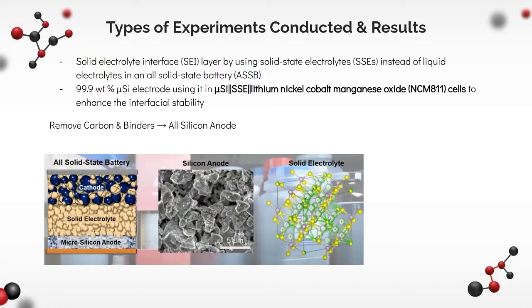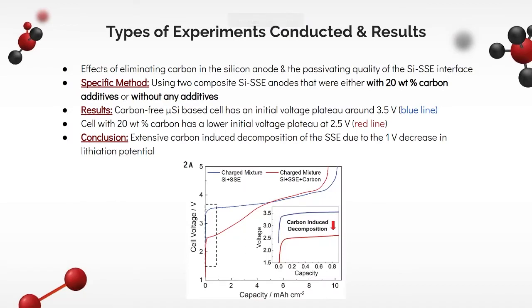Researchers removed all carbon binders from the silicon anode, since carbon is known to reduce the stability of sulfide solid-state electrolytes, promoting its decomposition. Researchers analyzed the effects of eliminating carbon in the silicon anode and the passivating quality of the Si-SSE interface. They prepared the samples using two composite Si-SSE anodes that were either with 20 weight% carbon additives or without. Figure 2a illustrates the voltage profiles of both cells during the first lithiation.